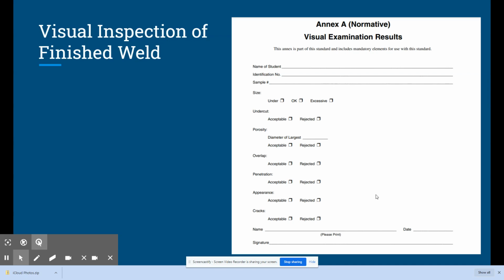And then obviously the most severe would be cracks. Any crack at all, even the tiniest little bit of crack on a weld prior to bending. We don't like cracks because cracks propagate, meaning as the material is stressed, cracks will grow. So if you've got a part that you put into service and it has a tiny little crack on it, if it's being put under load, that crack's going to grow over time.